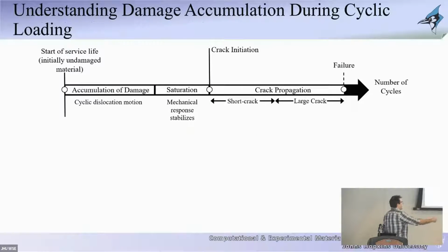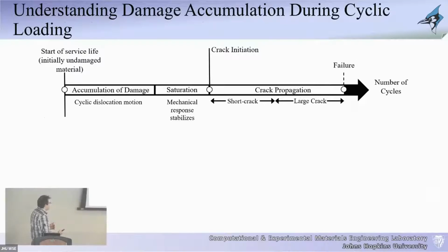So if you look at the life of any component in service, whatever application that is, and we're talking about metallic components here, typically if you have an undamaged, pristine material that just came out of manufacturing, and now it's exposed to this type of cyclic loading, initially the damage will continuously accumulate in the material as the number of loading cycles increases. Eventually there is a stage of saturation where nothing really changes much in the material. And then suddenly you get these cracks that initiate. The cracks then form what are known as short cracks, short relative to the dimensions of the material itself or the component itself.